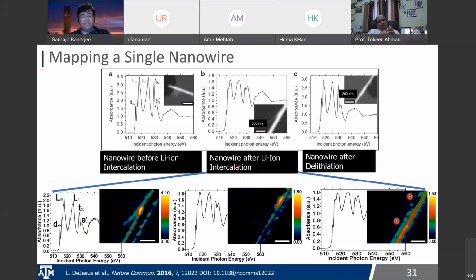This corresponds to a pretty high degree of lithiation, right? So essentially what you're directly measuring is lithium ion concentration and the extent of vanadium reduction. And so we are seeing some pretty large discrepancies even within one particle. You've got different amounts of lithium even inside one particle. And so why is it that the lithium is not freely moving?